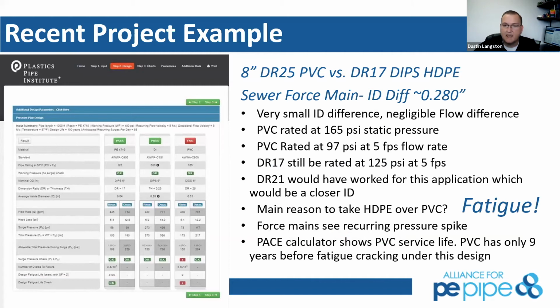And so they came through and said, hey, we want to upsize. I'm like, you probably don't need to upsize, because they wanted to put in a very, very thick DR11 for this application. And so we did a side-by-side comparison again. DR17 is rated at 125 PSI, and that is at 5 feet per second. They had a very, very high flow rate on this. And I think they were using a DR25 PVC. And come to find out, we can go with a very thin DR21 polyethylene and keep those same inside diameters pretty close. And they were able to use polyethylene without having to do that upsize.